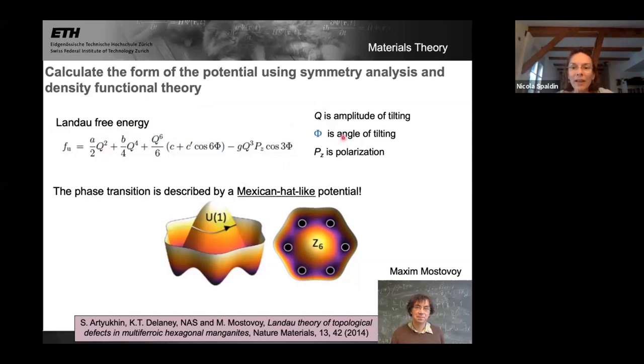Phi is the angle of the tilting. And I want you to notice that the angle of the tilting, I said there were three possible lowest energy choices, but notice that the angle comes in only at extremely high order, only as Q to the six or Q cubed P. And P here is the ferroelectric polarization. So the ferroelectric polarization, the electric dipoles, are actually not the primary order parameter for the transition. And this is also important because it means that their electric fields don't dominate and start causing trouble at the phase transition. They don't take over the physics from the intrinsic Kibble-Zurek physics.